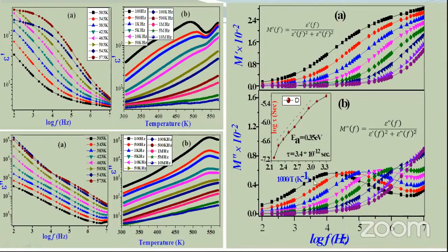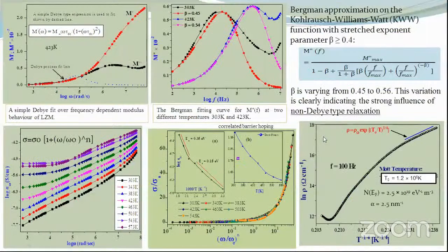There are various peaks in the complex part of the electric modulus. This shows the thermally activated nature of the material, because the peak shifts towards higher frequency range with increase in temperature. From these peaks, we have calculated the activation energy, which is 0.35 electron volt. And we have used various other models to fit the peaks.